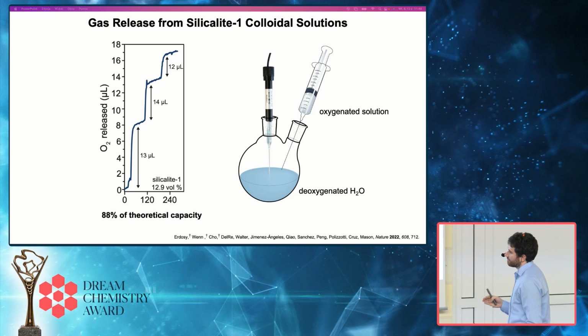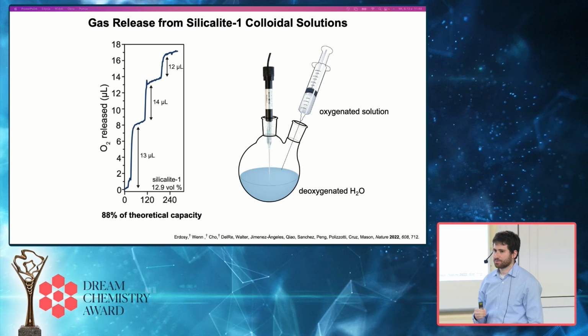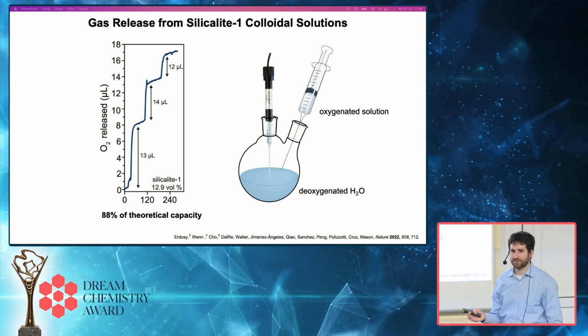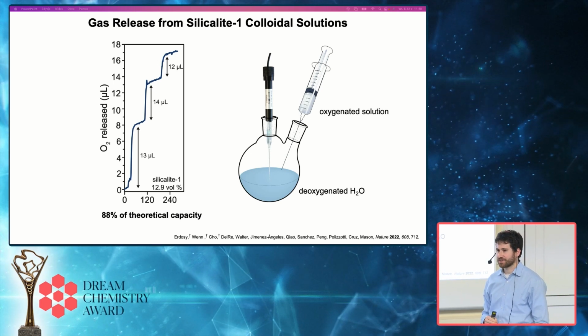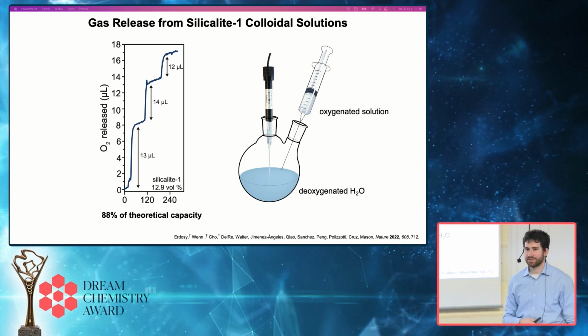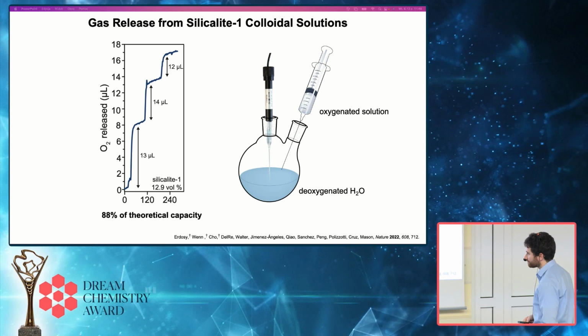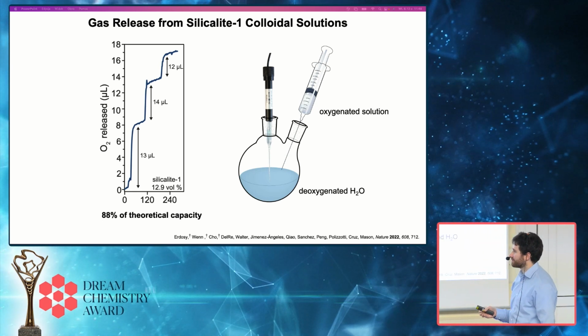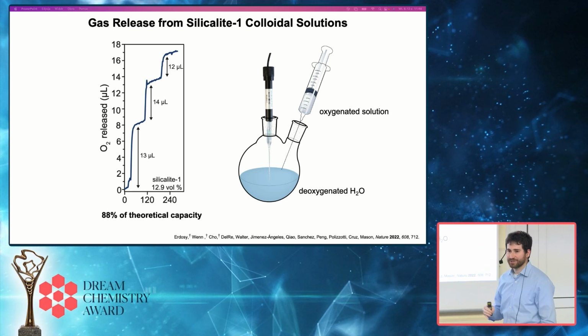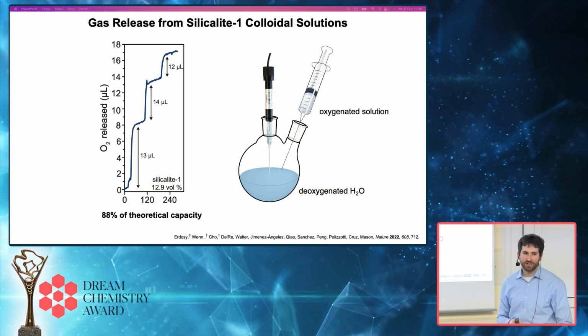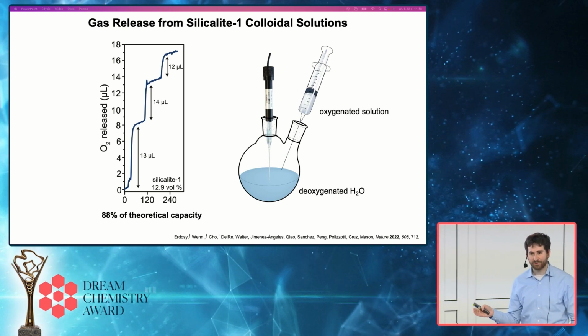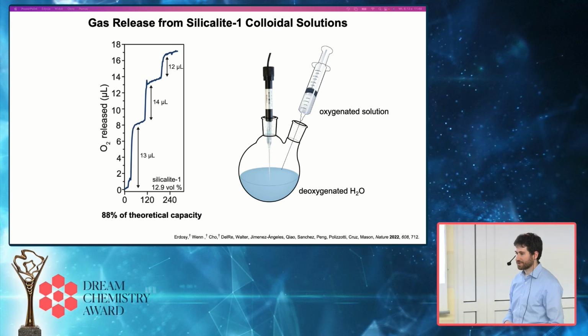And what we find is that the amount of gas that's released is very consistent with what we have measured directly with our gas uptake measurements and what we would predict based on the known adsorption properties of these materials. What we also found was that gas release was really fast, faster than we could measure in the time scale of this experiment, which is consistent with what we see in molecular dynamics simulations.